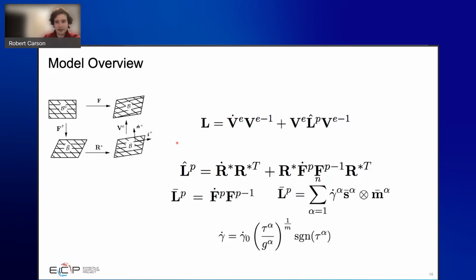We can also describe the velocity gradient in this B hat frame here as L hat P, which is made up of a spin term of our lattice and the rotated portion of our plastic velocity gradient. Our plastic velocity gradient, which is given in this line here, is directly related to the combined shearing of our slip systems. Our slip rate can be described using various different equations, but for a lot of what we're doing here, we're just going to make use of a basic power law, where tau is our resolved shear stress on a given slip system, and G is our critically resolved shear strength for a given slip system.